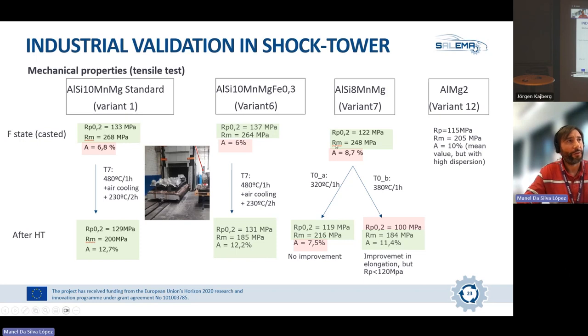We also tried an aluminum silicon 8 manganese magnesium variant. With that, elongation was closer, so we wanted to try a different approach that is better seen by end users. Instead of a complex T7 heat treatment that requires heating at very high temperature, we went for a short annealing. We tested 2 different temperatures. With the first one at 320 degrees, we didn't see any improvement in mechanical properties. For the second one at 380 degrees Celsius, we reached the required elongation, but we lost some yield strength that went below the minimum requirement.